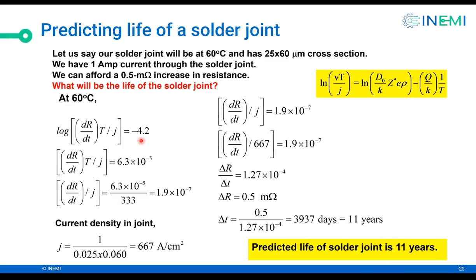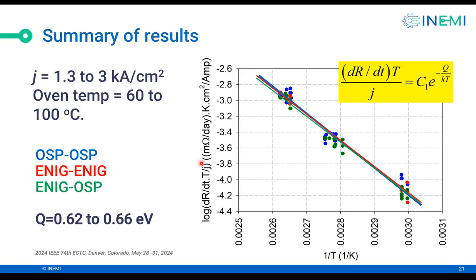Now, this first term, log of dr over dt times temperature divided by J, we obtain from this plot. So given the temperature, we know 1 over T, and then we can find this term. Once we know that term, we know what temperature is, we know what current density is, so we get dr over dt is 1.27 times 10 to the minus 4, and we say that the failure criteria is 0.5 milliohms dr, so we can find dt as 11 years.